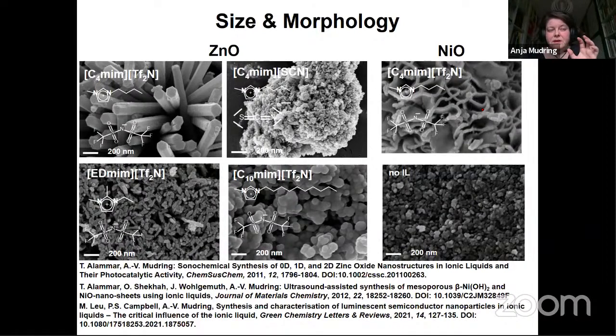And the effect of the ionic liquid is really very distinct. On the right side, you see nickel oxide that we prepared by a similar reaction route in an ionic liquid, and you see that we obtain nanosheets. When we leave out the ionic liquid, you see that we get small round-shaped particles. So there's this really distinct effect. And by a smart choice of the cation and anion, you can tune the size and the morphology of your material.